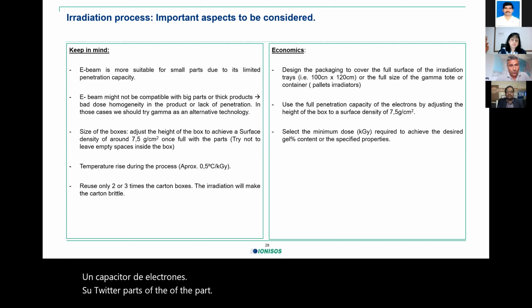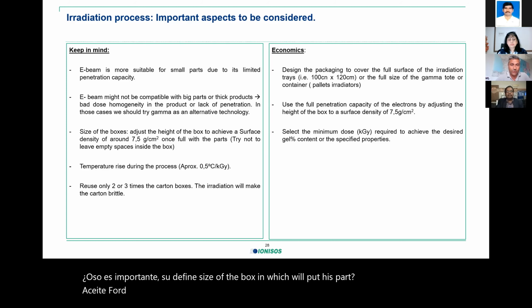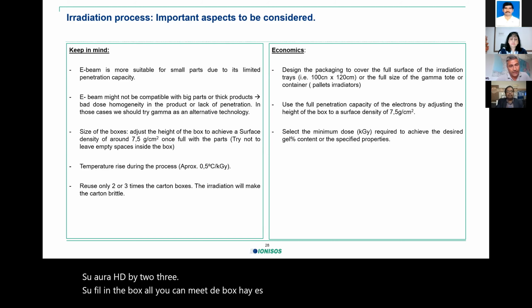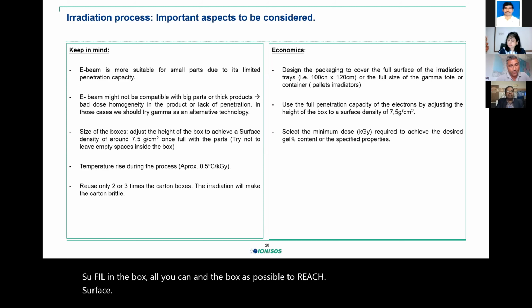Also, it's important to define the size of the boxes in which we are going to put these parts. As said before, the maximum penetration capacity of the electrons is 7.5 grams per square centimeter. So our advice would be to fill the box as much as you can and make the box as high as possible to reach that surface density, and don't leave empty spaces in the box if possible.